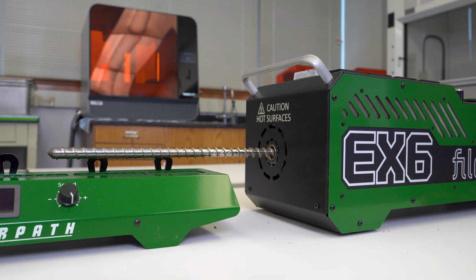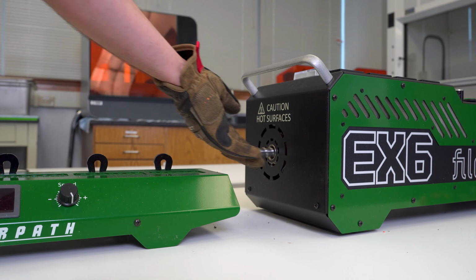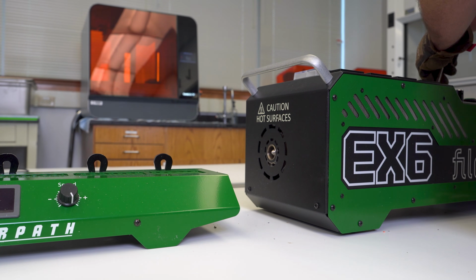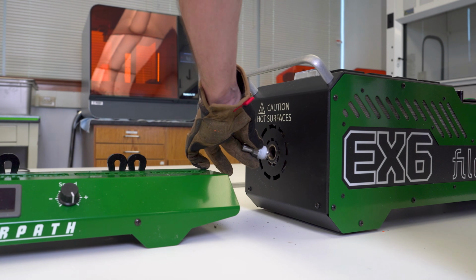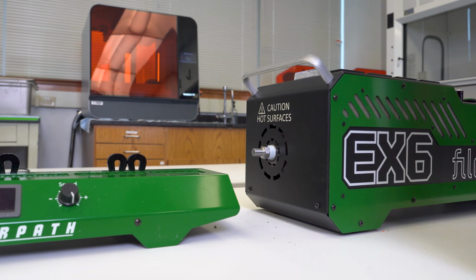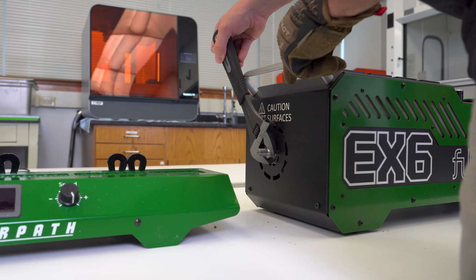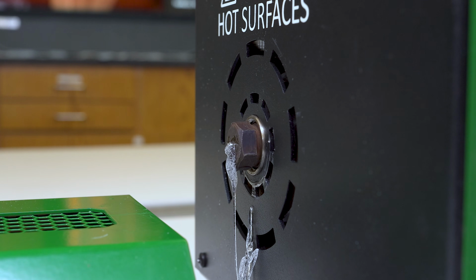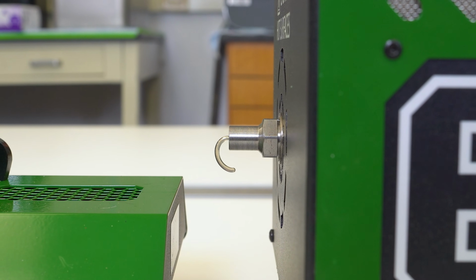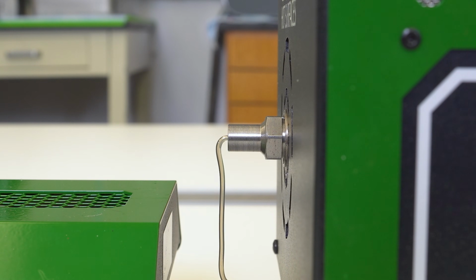As discussed previously, we will swap out the standard screw for a more aggressive high compression screw for this very reason. We also need a longer die because counterintuitively, PETG can drool when coming out of the die, which you can see now when a standard length die is used. This may defy your expectations because PETG should maintain its shape upon exit from the die because of its high melt viscosity. Well, viscosity decreases with temperature and the high forces associated with the screw can overheat the material.